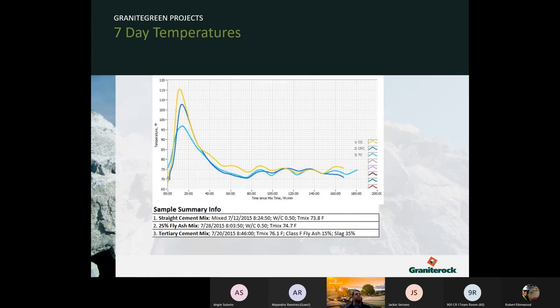To give a visual of the heat given off with different levels of SCMs, the yellow line is the control using all Portland cement. The dark blue line is cement with 25% fly ash. And the third is 50% cement, 15% fly ash, and 35% slag, dropping the heat down quite a bit. This also shows that with less heat, the slower the set. So that has to be thought about when placing concrete.